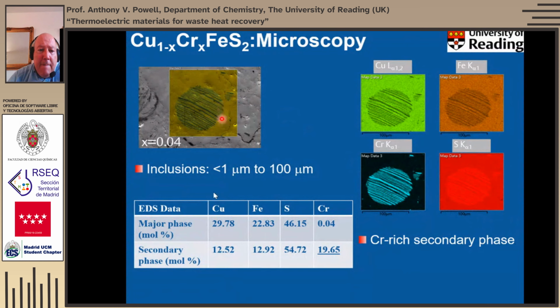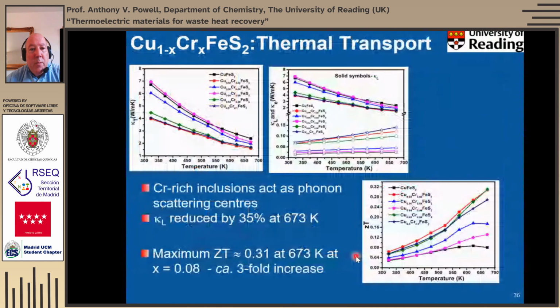And we found that the EDAX, or the energy dispersive X-ray data from the microscope, tells us that whilst the major phase is consistent with a chromium-doped chalcopyrite, these inclusions, this secondary phase for instance, is a chromium-rich secondary phase. We think that is what is affecting the carrier concentration in a non-systematic way, because it will depend on things like thermal history in terms of the formation of those inclusions. And we think that that is actually what's causing that apparently random variation in the electrical transport properties.